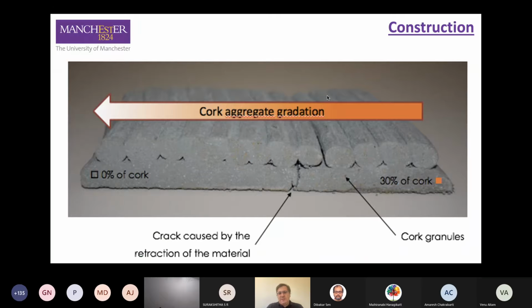This is one of the first examples of the printed structure. So we started in one side printing concrete and 30% of cork, and gradually the composition changed, and at the end we finalized by printing only concrete. So as you can see, some problems, some cracks, some pores due to the lack of process optimization.